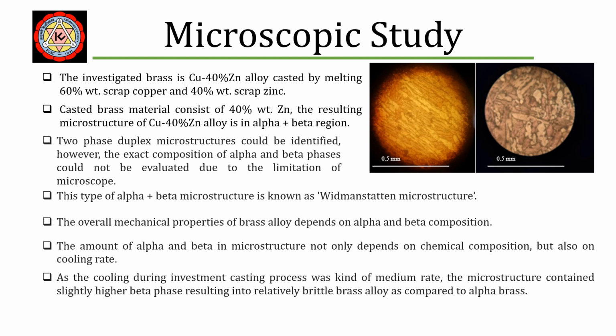The investigated brass is a 60% copper and 40% zinc alloy, casted by melting 60% by weight scrap copper and 40% by weight scrap zinc. The casted brass material consists of 40% zinc by weight. The resulting microstructure of the copper-zinc alloy is alpha and beta region, because the solubility limit of zinc in copper is about 35%.